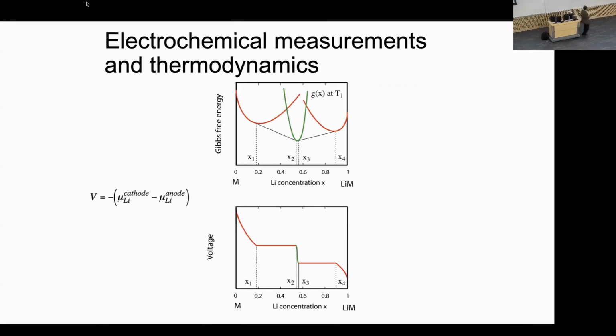And you can make that a little more complicated. So often you might have an intermediate phase that's stable. This happens when maybe the lithium ions and the vacancies order. And then in that case, you break this common tangent, you create two new common tangents. And so that translates in the voltage curve to two plateaus that are separated by a step.